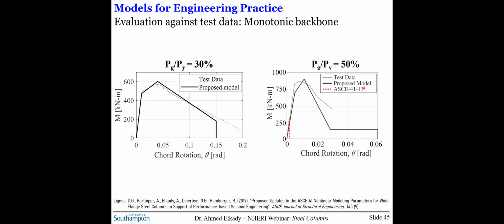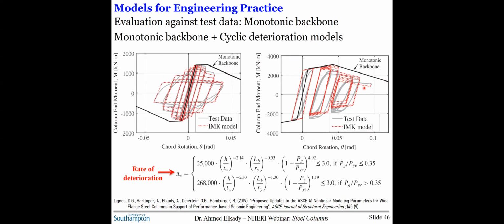This is the same, again, these are all some evaluations showing good agreement between the proposed monotonic backbone curve and the test data at different axial load levels. I mentioned that these monotonic backbones can be used with phenomenological component models that simulate cyclic degradation, strength, and stiffness.